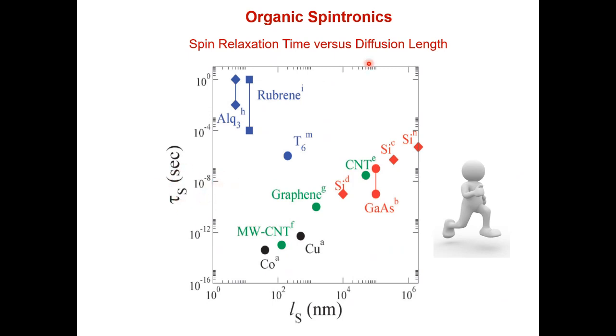And now there might be a future for organic spintronics, because we know that since we have very light atoms in organic molecules, there is a very, very slow spin relaxation time. So we keep the spin over a large distance in organic material. But the problem right now is that the diffusion length is quite limited. If it would be improved, we will have a new generation of organic materials for spintronics. But this is maybe what we will see in the future.